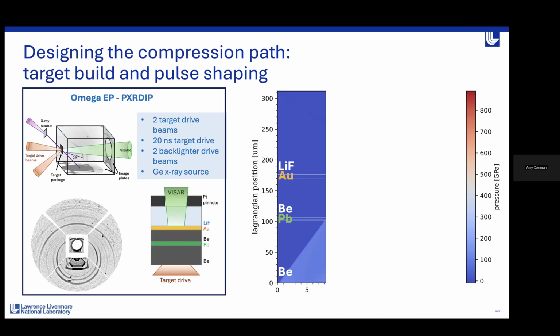What this allows us to do is calibrate our diffraction patterns so that we can correctly pull out a density of our sample layer. On the right-hand side, I'm going to show a hydrocode simulation of this experiment. These experiments, as you can imagine, are quite difficult to field, and we really do rely on hydrocode simulations to do the design work, not only so we can reach the correct pressure and temperature states, but also so we know when to probe with our diagnostics.